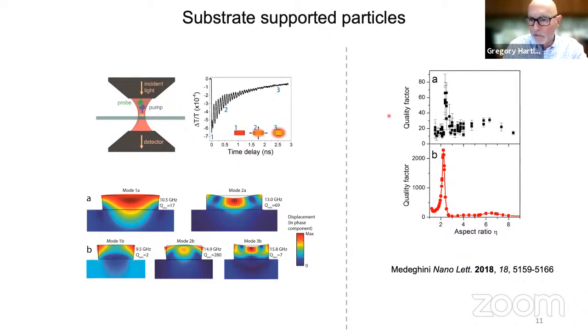What I want to focus on is the lifetime, expressed as a quality factor, basically the lifetime divided by the period. What you see in general is quality factors between 10 and 20. This is typical of a structure that's stuck onto a surface. These are very similar to the numbers that Stefan's measured in his lab. What's happening here is that you're losing energy. You have sound waves radiating into the glass or the support of the structure, and that's taking the energy away and causing the damping. This is like radiation damping, like what you get in optics, but it's radiation of sound waves.